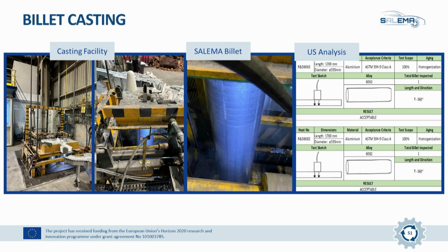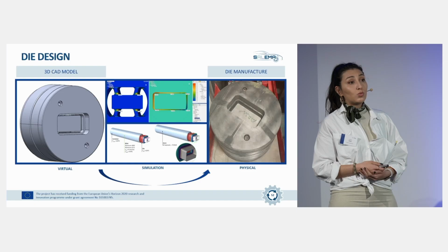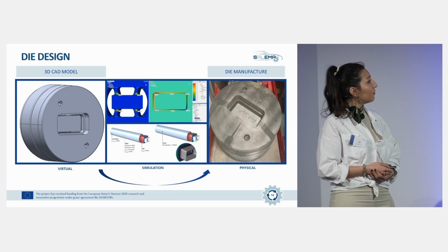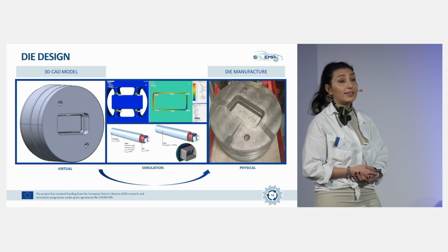They have been analyzed ultrasonically in order to see if there are any defects in the billet. It's a non-destructive testing methodology. If there's a void, if there are impurities or something like that, we have tested, and results are acceptable with respect to ASTM standards.